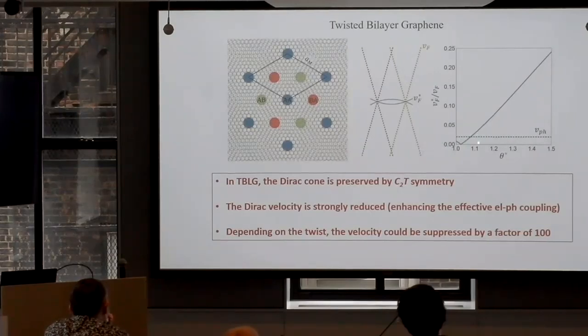So I will do a theory which would not be valid over here because Migdal's approximation will fail when the velocity is lower. But I have a theory which is reasonable over here. Monolayer graphene is somewhere up here, way up, like 5 degrees or something. And there are all these symmetries that we're taking. I'll come to symmetry later on. Depending on the twist, the velocity could be suppressed by a factor of 100.